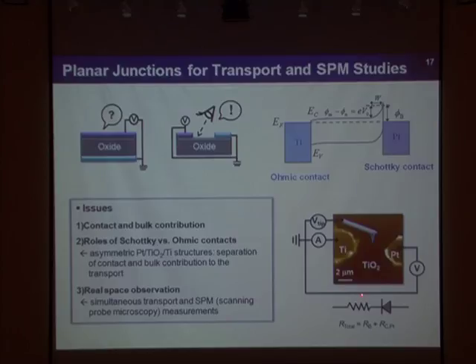From this device we can measure the IV characteristics, and at the same time characterize the surface using AFM technique. So we can clearly understand the contact and bulk contribution to the total resistance, and also get a clear idea about the Schottky and ohmic contacts in real space observation.